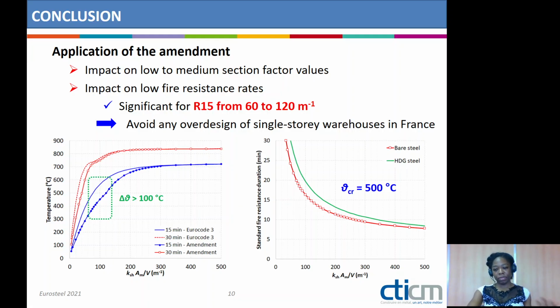And if you consider bare steel or hot dip galvanized steel members and a critical temperature of 500 Celsius degrees, you can see that for a section factor of about 150, the standard fire resistance duration stays below 15 minutes. However, when you apply the amendment, you can have a standard fire resistance duration that is higher than 15 minutes, well, slightly higher, but you can see in the specific case that it is quite unnecessary to over-design the cross-section of this member just by applying hot dip galvanizing.